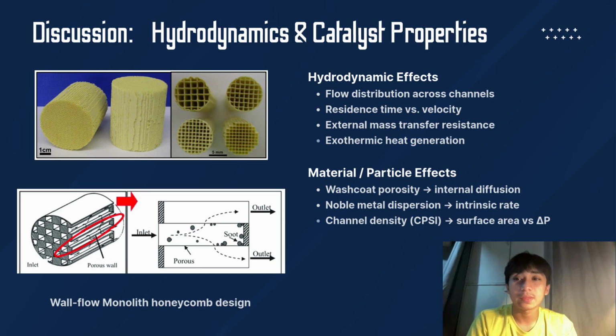with the active sites. The reactions occurring in the monolith are also highly exothermic, which can create temperature gradients that affect catalyst stability. At the material level, the washcoat layer on the channel walls contains porous materials and dispersed noble metals. Washcoat porosity controls internal diffusion resistance, while noble metal dispersion determines the intrinsic reaction rate. Therefore, the overall catalytic performance depends on the interaction between the honeycomb reactor design, flow behavior, and particle-scale transport phenomena.